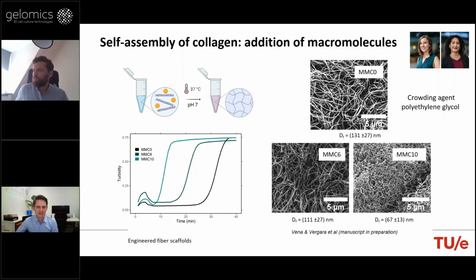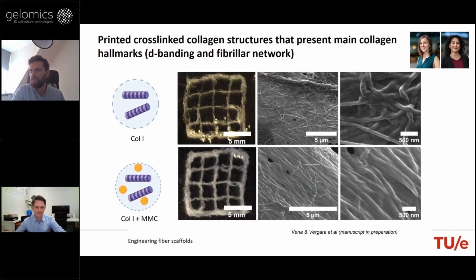You can. What was very interesting for us to see, and I think in this slide I only mentioned very briefly, is that these printed constructs were stable up to 2 months. We believe there was some sort of native-like cross-linking going on in there that did not require any addition of cross-linking agents like the transglutaminase that you were mentioning. Here we were really just playing with the pH and the ionic concentration of the bath, and then of course the confinement that led us to a stable collagen network formation. But of course, I would be very hesitant to say that they are fully cross-linked and how. This is something that we are now investigating.